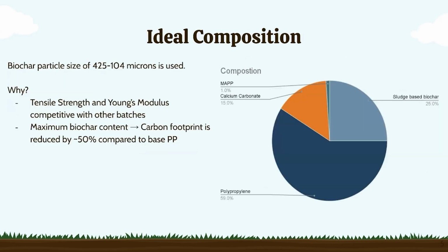The ideal composition we landed on was a mixture of 25% sludge-based biochar, 59% polypropylene, 15% calcium carbonate, and 1% MAP, and with a biochar particle size of between 425 and 104 microns. Since the tensile strength and Young's modulus were pretty competitive across each of the batches, we were able to prioritize biochar content for our decision, thus leading us to a roughly 50% reduction in carbon footprint compared to base polypropylene.